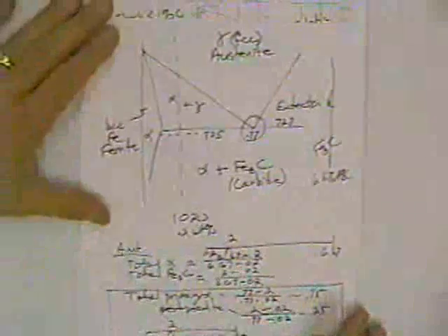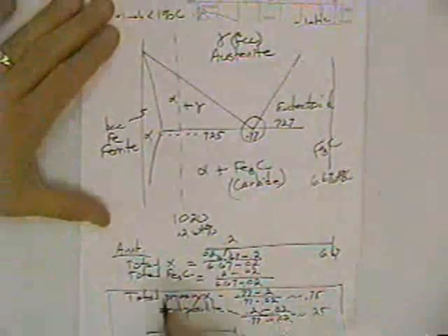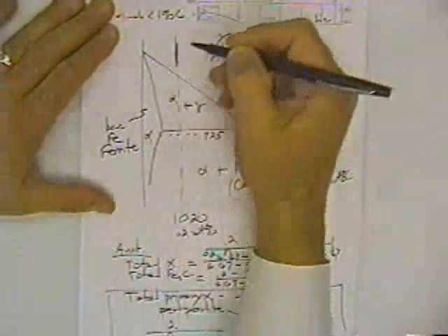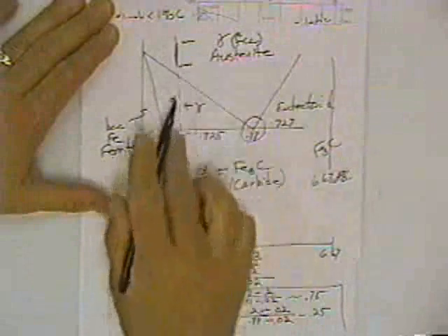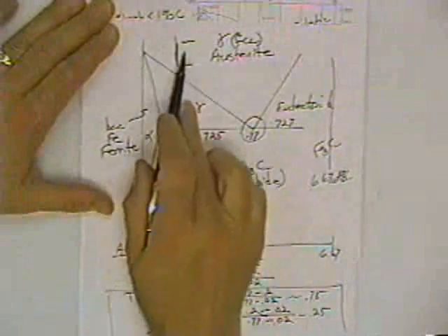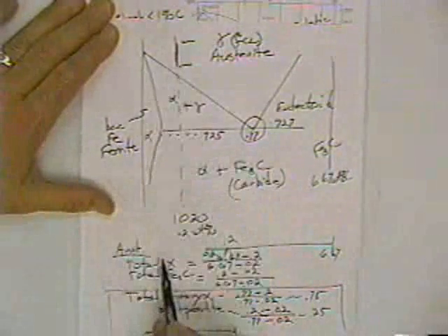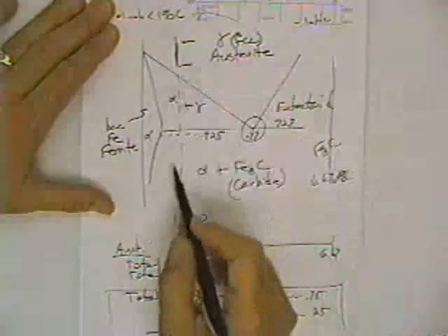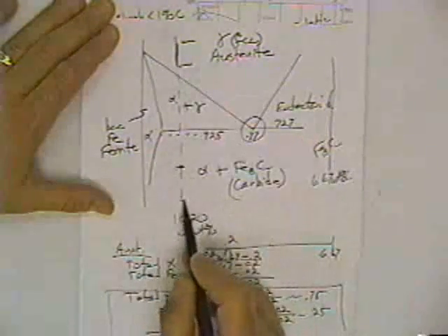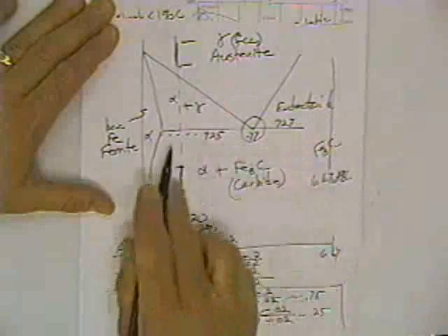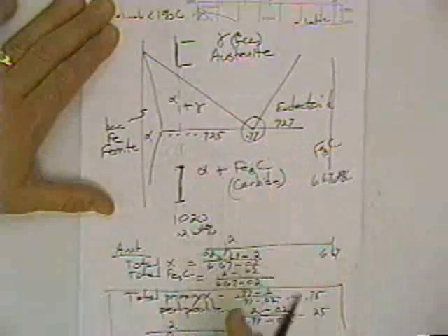And for the heat treatment of steel, if you could put the picture back on, the first step is going to involve forming austenite. So in the heat treatment, we're going to heat above these phase lines, phase boundaries, and into this austenite phase field. We'll quench it, and then when we do the tempering process, we will heat below this line 727, which is called the A1.